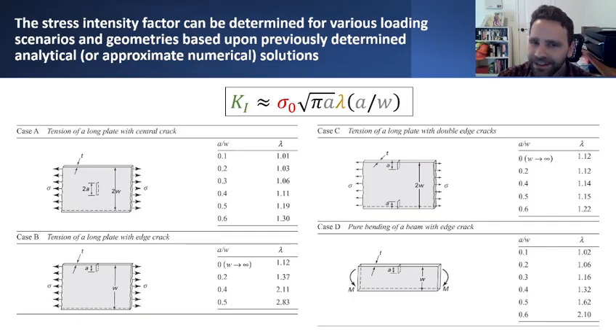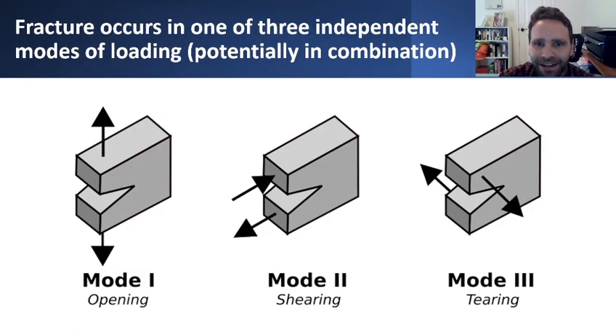situations. To analyze this, there are really three primary modes of fracture which can occur and which result in different appearances in how those stress fields will manifest close to the crack tip. And they can be categorized into mode one, which is a classical opening mode of fracture where the material is literally pulling apart. Mode two, which is kind of like a shearing deformation as shown in this middle figure here, where it's kind of like you're pushing in the top half of this block of material and pulling the bottom half out and generating a fracture through kind of a shearing mechanism.